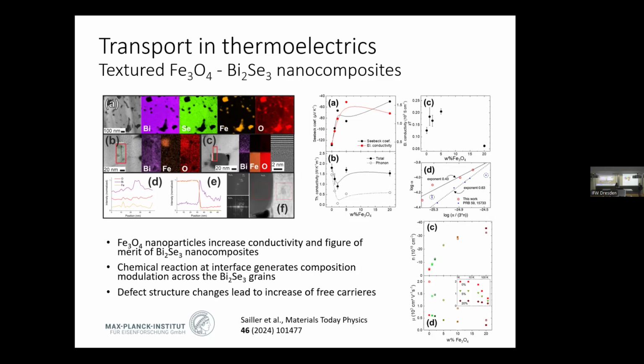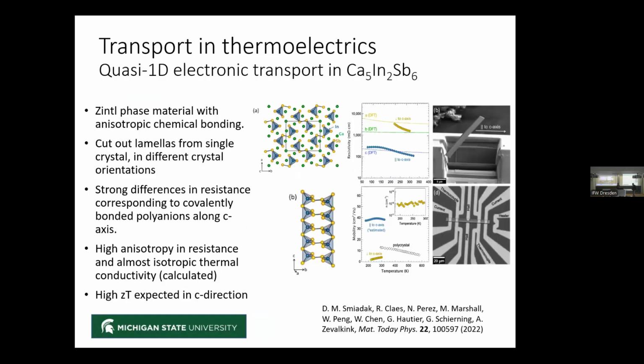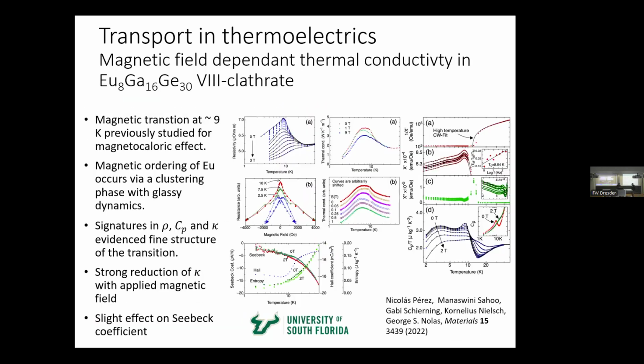Actually, I also wanted to ask about this interest on the first slide. It is interesting for me because we got the magnet from IFW, and we now have the possibility to measure up to 16 Tesla, and therefore these effects are of interest. I saw somewhere a very strong dependence on the magnetic field, probably of the thermal conductivity, as a function of magnetic field. Actually, what is the mechanism for the strong reduction with applied magnetic field?